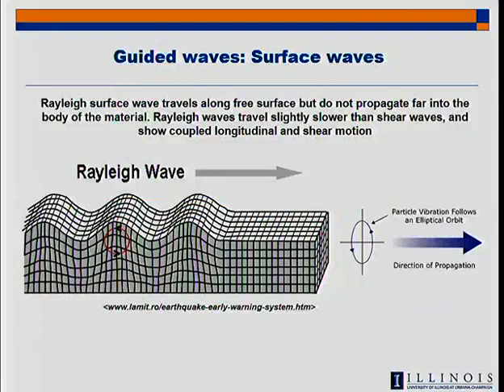Well, we can use another wave, which is a combination of P wave and S wave, that is compressional and shear behavior. And these are called surface waves. You send and receive from the same surface. They propagate along the free surface. Those other waves propagate in every direction in media, like my voice. I mean, it's directed in this way, but if you're standing over there, you hear it. It goes in all directions. These stick on the surface, and they only penetrate a certain distance below the surface. They're not very big. They penetrate about a wavelength, remember that spatial characteristic, below the surface. So with these waves, we're able to characterize the surface, but only to a certain depth.